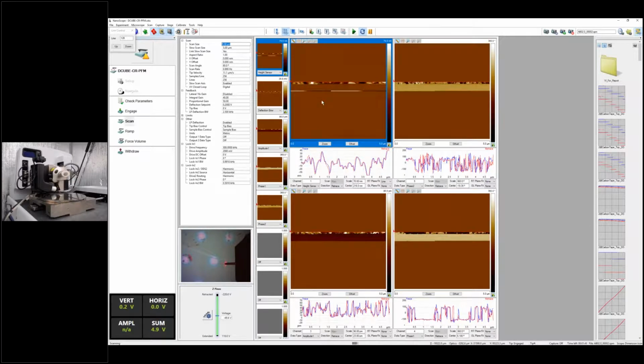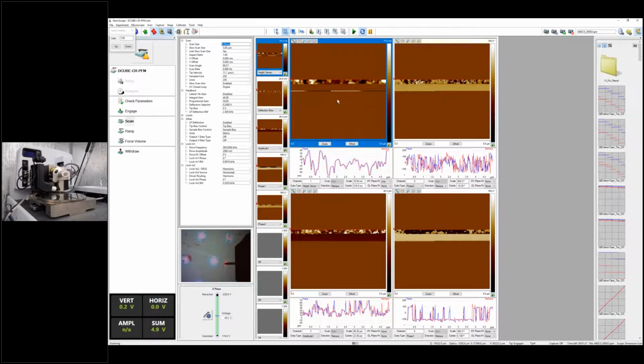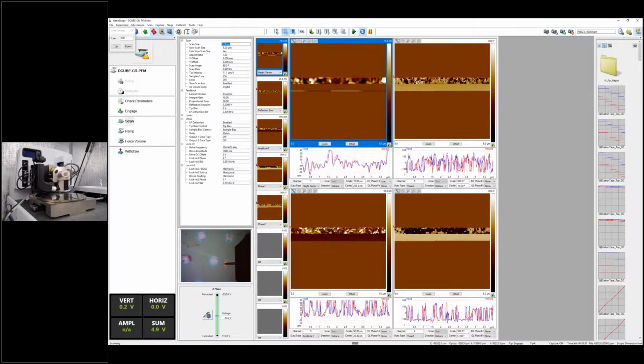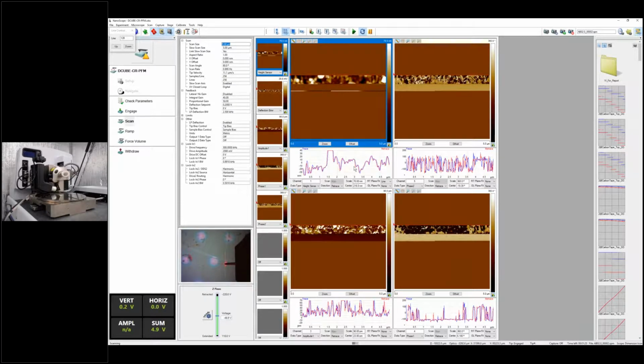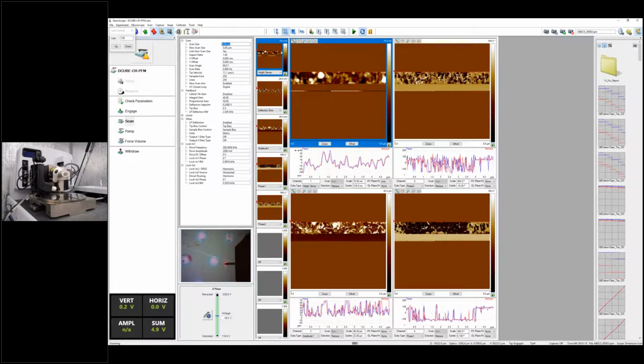So this surface is not very flat. I know nowadays some of the ceramic films can be really, really flat, and 2D materials are of course even flatter. But this one is relatively rougher. Peak to valley is about 50 to 100 nanometers. So we are now in contact mode, which means we maintain the force on the cantilever